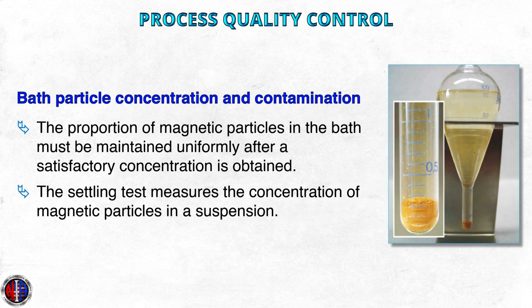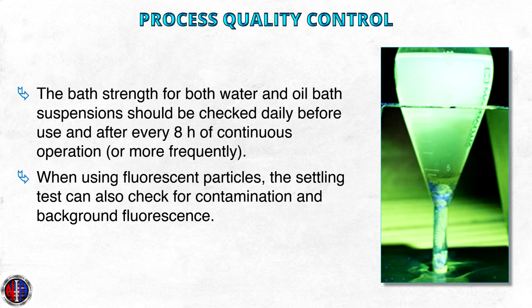The settling test is intended to measure the concentration of magnetic particles in a suspension. The bath strength for both water and oil bath suspensions should be checked daily before use and after every 8 hours of continuous operation. The recommended range for particle concentration is 0.1 to 0.4 milliliters per 100 milliliters for fluorescent particles and 1.2 to 2.4 milliliters per 100 milliliters for visible particles.